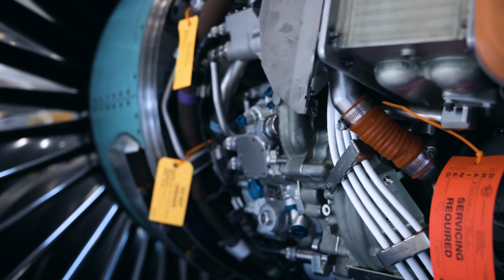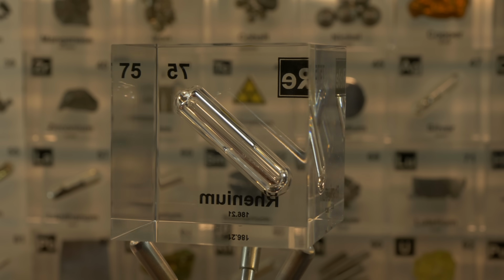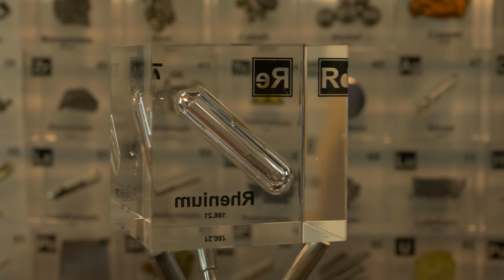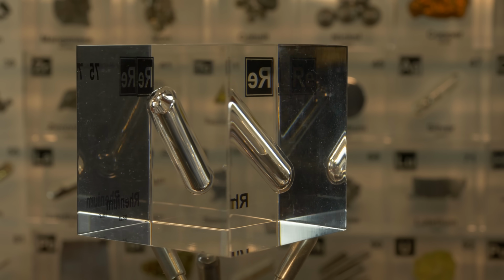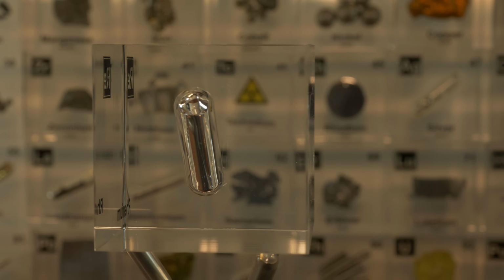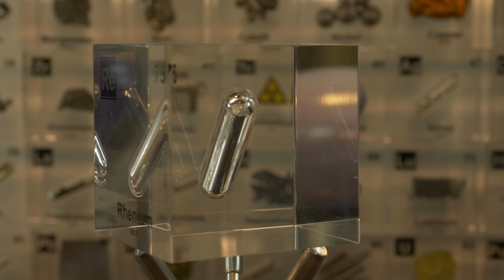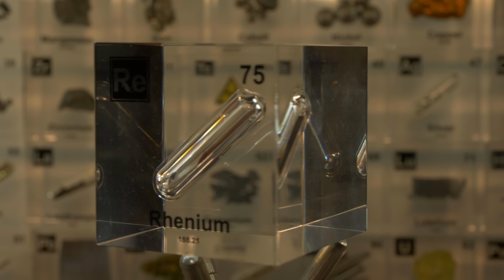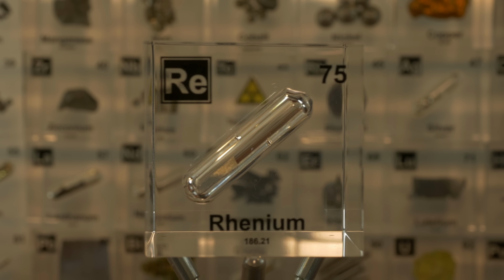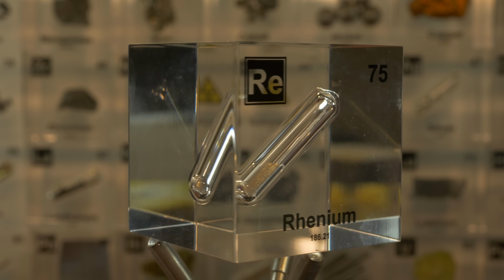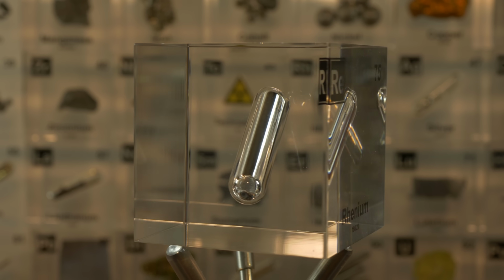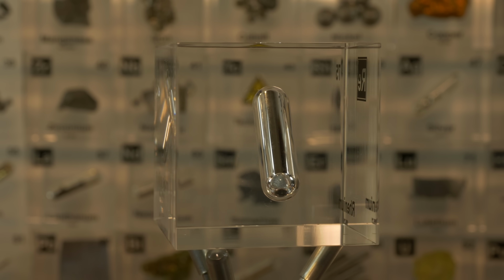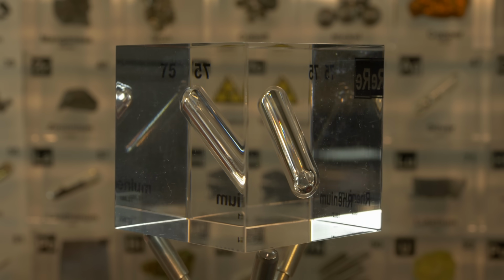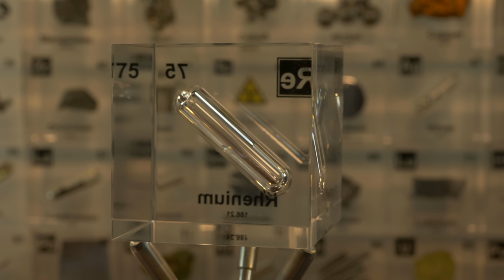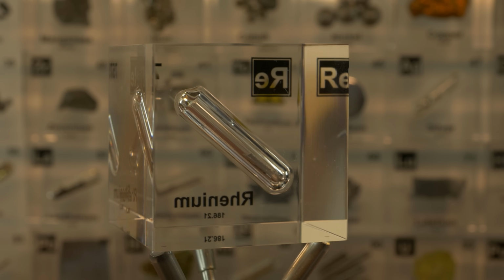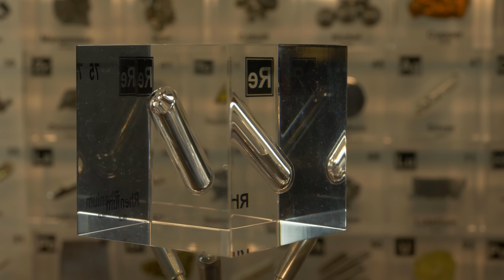By adding a small percentage of rhenium, typically 3 to 6%, to nickel-based alloys, metallurgists found that the alloy's creep strength, its ability to resist slow deformation under high heat and stress, is greatly improved. In essence, rhenium strengthens the alloy at high temperatures, allowing engines to run hotter and more effectively. For example, second-generation single-crystal turbine blade alloys contained about 3% rhenium, and third-generation alloys ramped that up to around 6% rhenium.